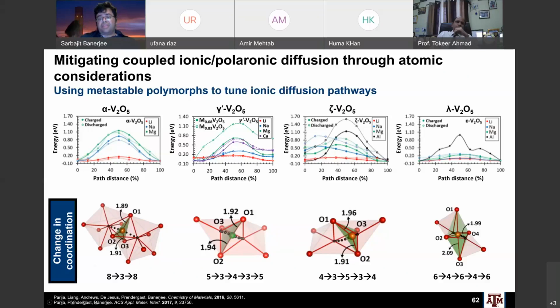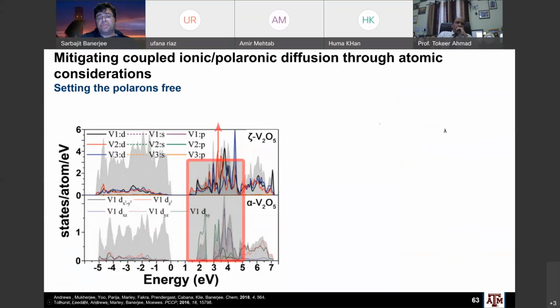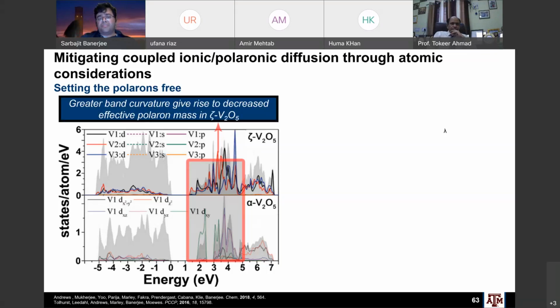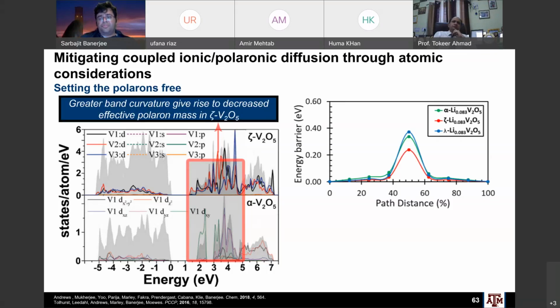Okay, so this makes life a whole lot easier, and this is a major issue from the perspective of electronic structure. I showed you the problem with square pyramids. This dxy is split off, and it's at the bottom of the conduction band by itself. And because it's a narrow 3d band, we get accumulation of electrons here that have a hard time moving through the structure. Over here, we get much more diffuse 3d states that are degenerate, and this allows us to move electrons more easily. And so there's still polarons being formed in these lattices inside zeta V2O5, for instance, but these polarons are much more readily able to diffuse through the lattice.